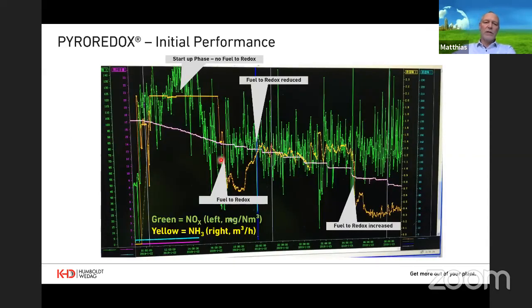If you look at the trends, they show you clearly what I've just mentioned. If you look, for example, at the green line, and the respective scale is here, that is the NOx emissions in milligram per normal cubic meter. And the yellow line is the ammonia injected. And you see, here's the startup phase, and there was no fuel put to the redox, which means the redox didn't work as redox, so it was off.